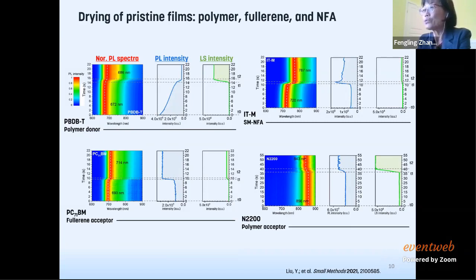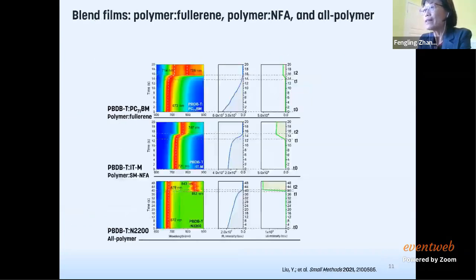This is the pure material. Then we will image, recording the signals from the blend. So we have 3 blends. Then we get 3 different kinds of signals. So these signals give us different information. For some materials, we can see that in different donor and acceptor combinations, the signal is dominated either by the donor or by the acceptor. It's a bit interesting for the polymer acceptor. They have 2 peaks after drying.